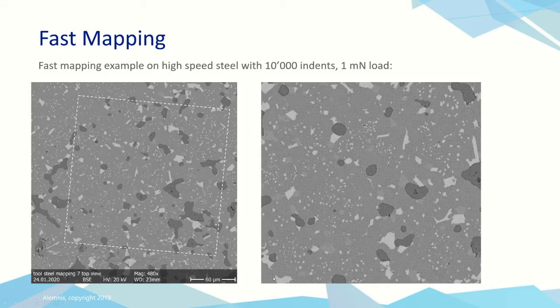Here's the same high-speed steel sample we saw earlier. So it's got 3 phases. The soft manganese sulfide grains here, the light gray carbides, and the ferrite matrix. The white dotted line shows the area where we've made an array of 10,000 indentations. And you can see those indents in lines across the surface here.